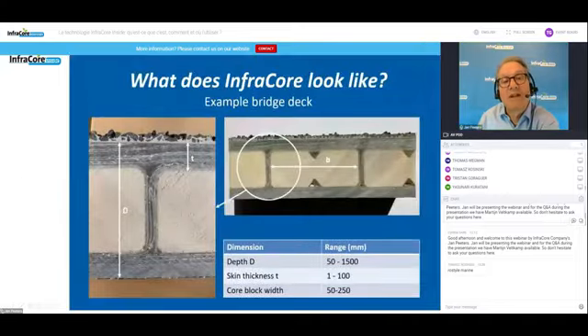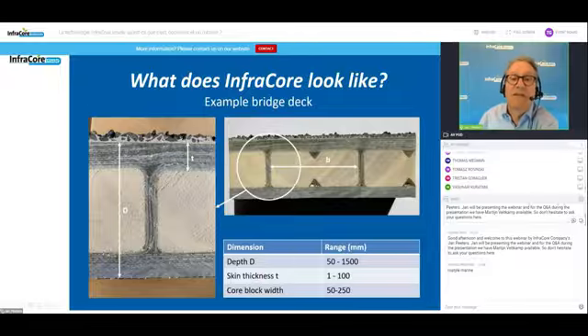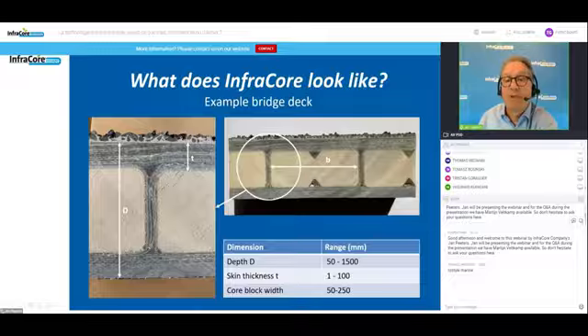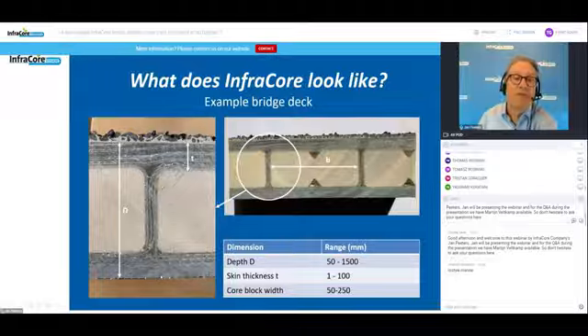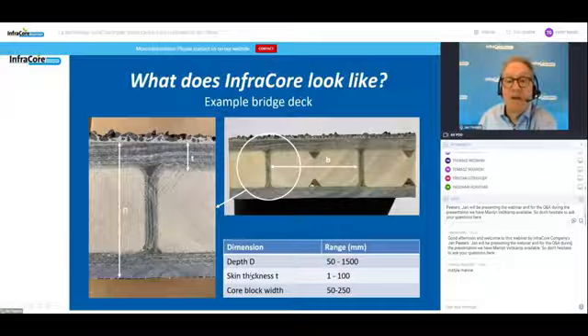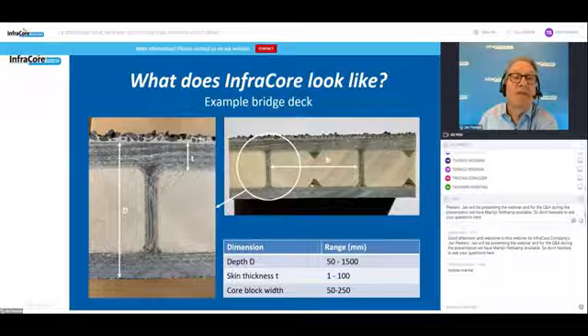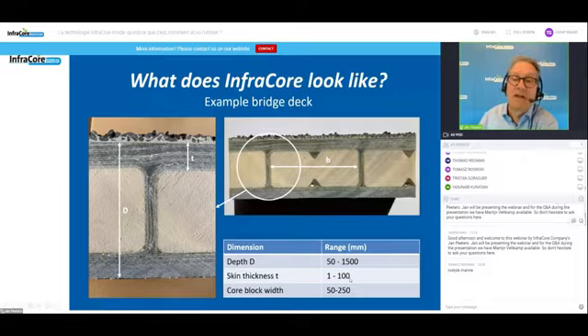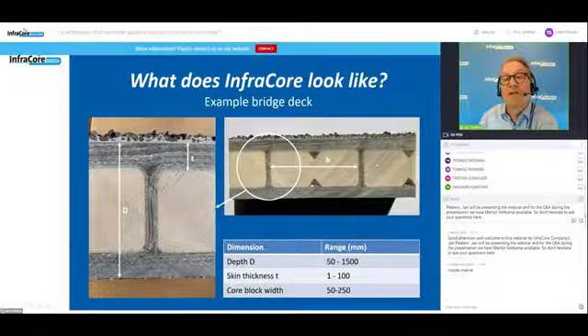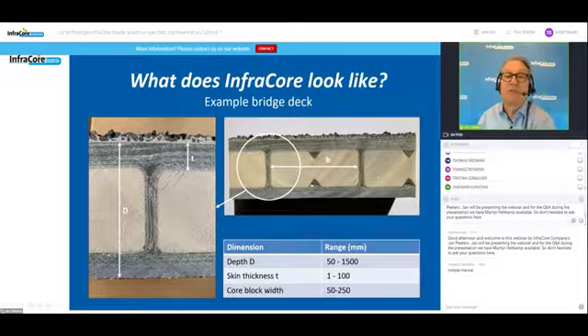Well, what does it look like in reality? This is a photograph of an actual InfraCore bridge deck. It's a tiny deck, 50 millimeters roughly. But what I've sketched here is that this dimension, the depth of the structure, can be between 50 millimeters and 1.5 meters. So we talk about serious depth of the sandwich structure. The thickness of the skins, here it's something like 12 millimeters. We can choose somewhere between reasonably 1 millimeter and 100 millimeters, 10 centimeters. And the width of the core blocks here is typically between 50 millimeters and 250 millimeters.